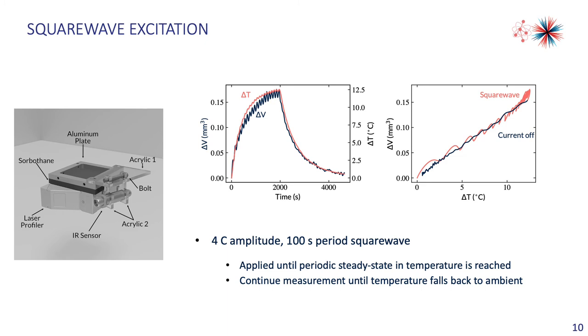both the temperature and expansion measurements were kept recording until the cell temperature fell back down to the ambient after the current has been turned off. So we can see in this experiment that the expansion is almost entirely thermally driven given the blue portion of the right hand side plot.